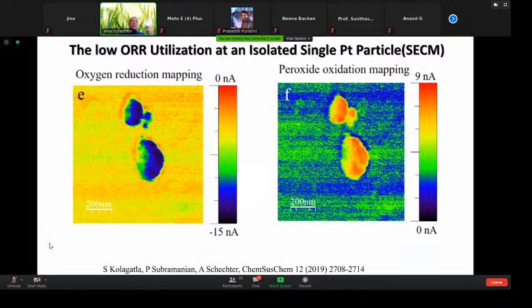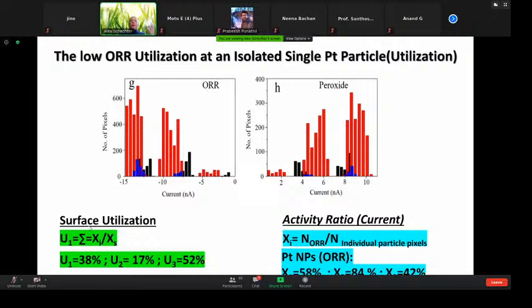But moreover, we can see that by using the platinum, we're using only a fraction of the activity of the platinum. Here on particle number 1, for example, we're using only 38% of the surface of the platinum. Particle number 2, 17%. So if we can improve that utilization, we can improve the platinum. We can reduce the platinum content in the fuel cell. We can still use platinum, but at a much lower content. Now that we know that we're utilizing so little of the platinum that we put in.